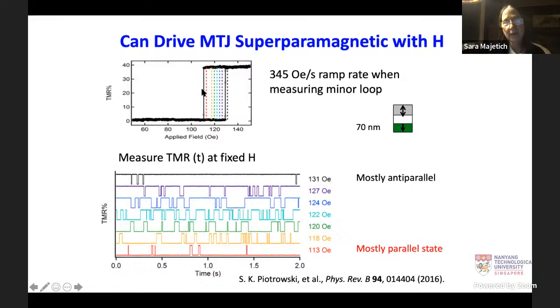So you would see this black curve, and this is with a particular ramp rate of the magnetic field. If you were to sit at a fixed field, shown in all the colored dashed lines, and measure the resistance as a function of time, you'd find that in the hysteretic region, it's actually switching once in a while back and forth. At 131 Oersteds, it's spending most of its time in the anti-parallel state for high resistance. But if you go down to 113 Oersteds, it's spending most of its time in the parallel state for low resistance. And so over a very small applied magnetic field, we can tune the behavior.